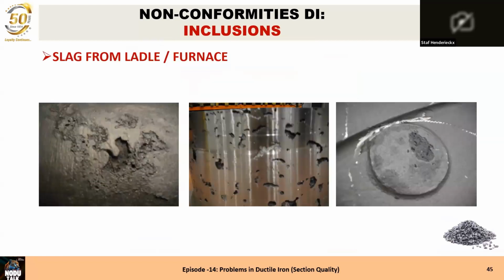You can see some of them here. On the left side, that's really slag. That's coming from the ladle. In the center, that's slag and even some gas. Wow, that was a very poor, badly poured casting. And on the right side, you can see it was slag and it went up to a boss which was on top of the casting, and it could not come out of the casting anymore, and it was stuck there.